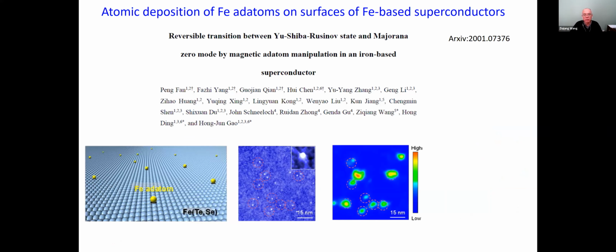That's a fair statement. In fact, the most convincing thing would be not to bother with the zero energy mode, but take a conventional superconductor that has strong spin-orbit coupling. Then you know that it's going to have some sort of a Z2 band structure. It's either trivial or non-trivial. So one can take a Z2 trivial band structure, but with strong SOC, take that kind of superconductor, and then put the magnetic ion on it, deposit on it. And one should see vortices. One should see a billion vortices, perhaps. And then if it's Z2 non-trivial, on the other side, then the vortices are actually non-abelian. Yeah, you're absolutely correct. Thank you.